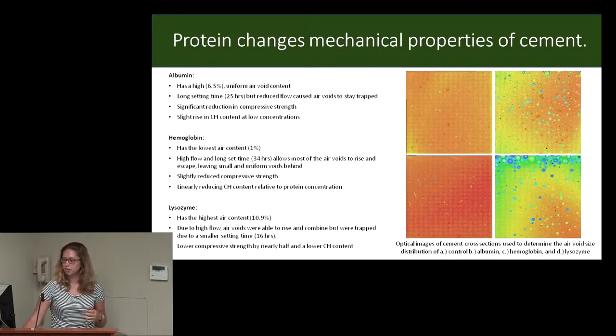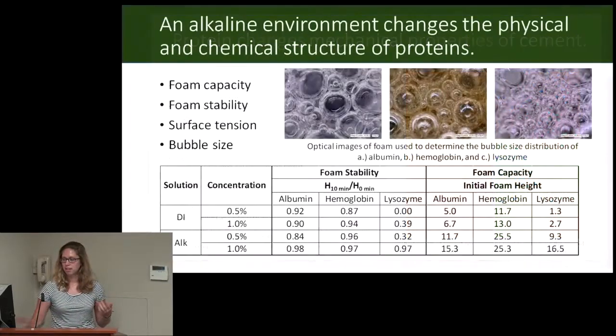With lysozyme, you can see this little middle area where the larger air voids joined together and rose to the top, but were stuck before the setting time allowed them to rise fully to the surface. Here you can see the proteins in the alkaline environment, where it lines up fairly decently with the stability capacity of the proteins. So we tested basic tests in these alkaline environments that are well known in distilled water and other materials, and compared them to our results in cement.